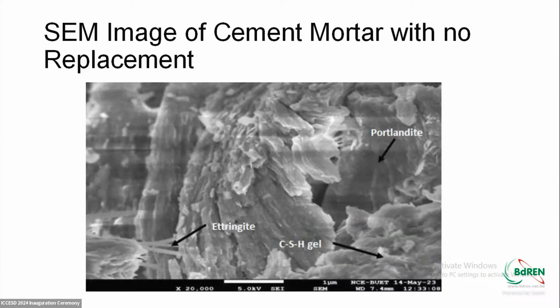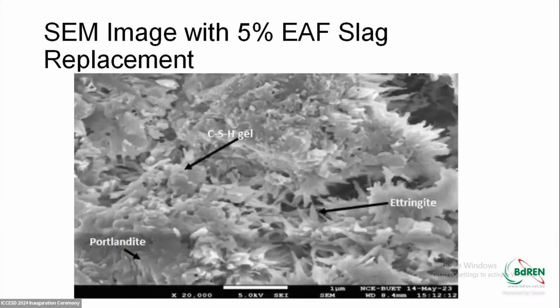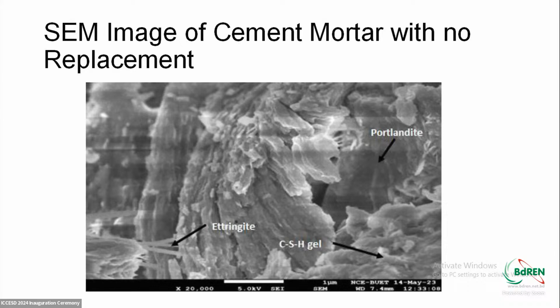Anyway, now we used scanning electron microscope to see the inner structure of these mortars. When there was no replacement, we can see the lighter shades are actually CSH gel, which contributes to the hydration process, and the elongated needle-like materials are ettringite, which fill the air gaps. The darker ones are Portlandite, which is responsible for density - it contributes to density, but if it is more than some allowable limit, it has an expansive property.